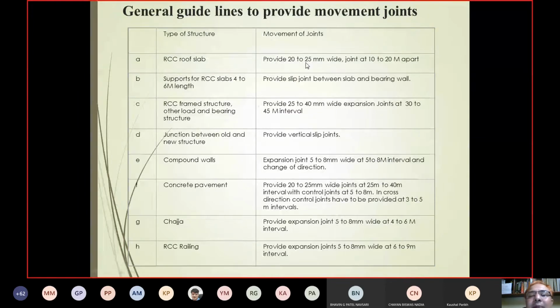In roof slab, provide 20 to 25 mm wide joints at 10 to 20 meter spacing. We have to provide that movement of joints. In support of RCC slab, 4 to 6 meter length, provide a slip joint between slab and bearing wall. In RCC frame structure, other load bearing structure, provide 25 to 40 mm wide expansion joint at 30 to 45 meter interval.